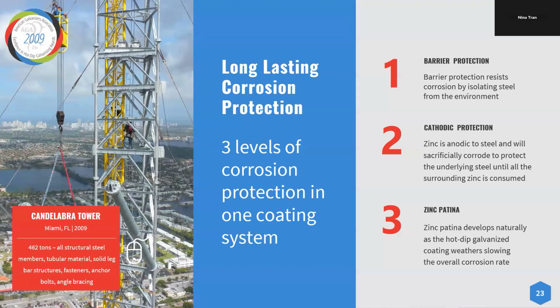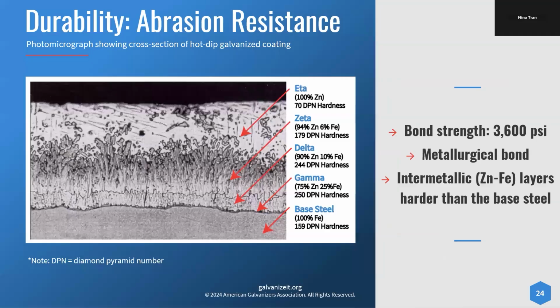which is impermeable. I can never say that word. It doesn't let water through, and it really, really slows down the corrosion rate. And the zinc patina can quickly develop as soon as a couple months up to a year. So that really slows down the corrosion rate of the overall system. But with one system, you get 3 layers of protection.